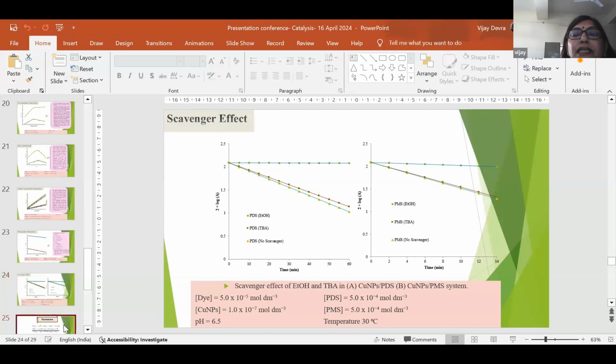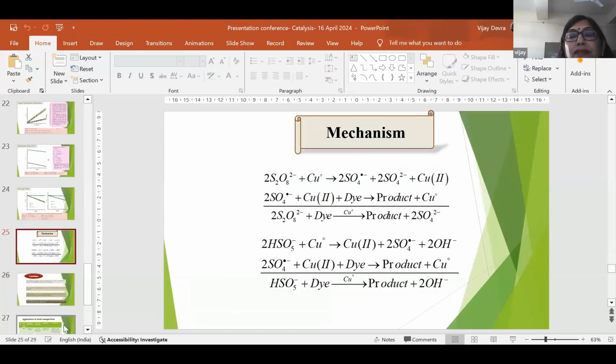It means the scavenger effect of EtOH, which confirms the formation of the sulfate radical in the reaction as an active species. This is the mechanism of the degradation of methyl orange in the presence of the sulfate radical and the copper nanoparticles. Copper nanoparticles convert into copper ions and sulfate radicals, and sulfate radicals then degrade the dye into harmless products, and copper nanoparticles are again regenerated.